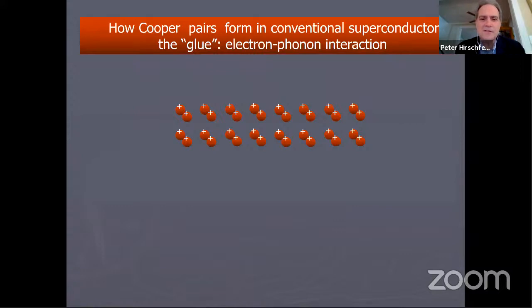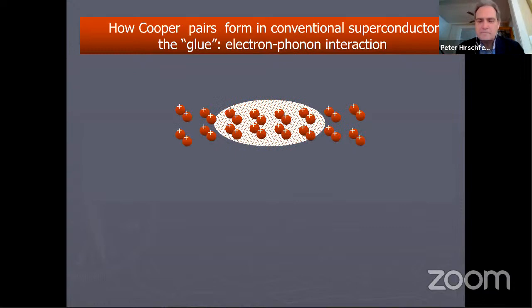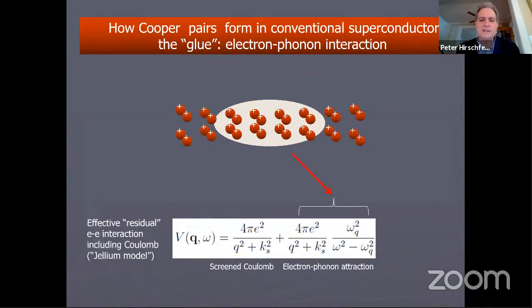The more exact picture, although it's still very approximate, is that you have an ionic lattice full of heavy ions, and then a light electron comes through with very high speed, the Fermi velocity, and polarizes the ions around it. This polarization lives for a relatively long time because the ions are heavier than the electrons, and gives a second electron going in the opposite direction time to come along and take advantage of this polarization.